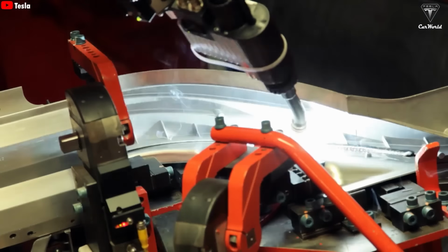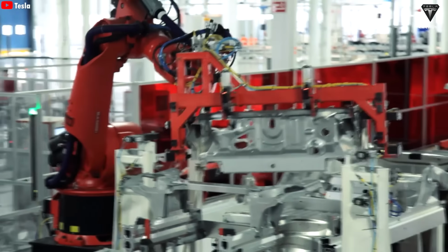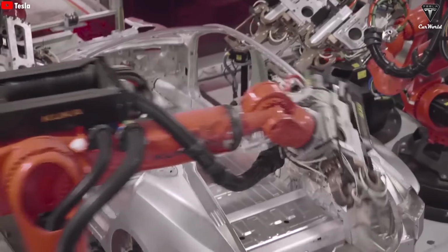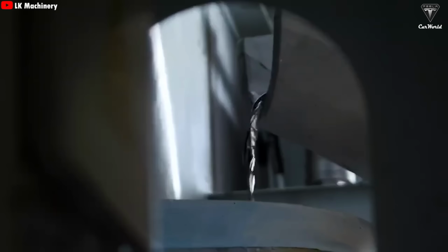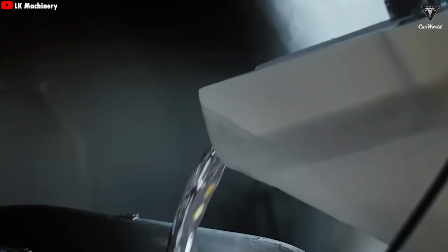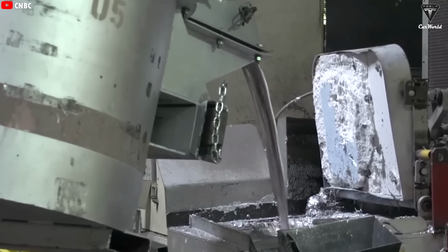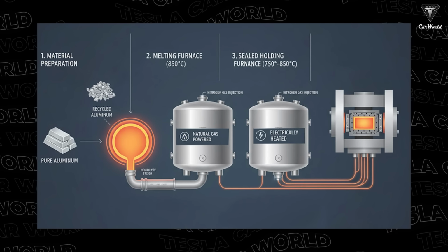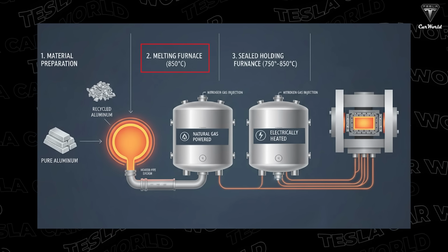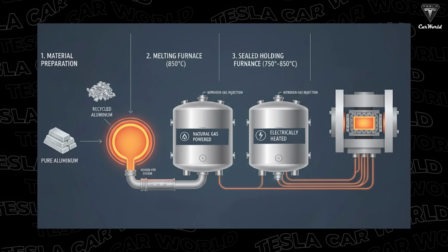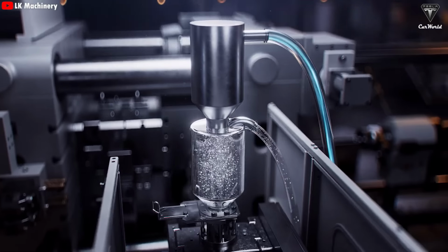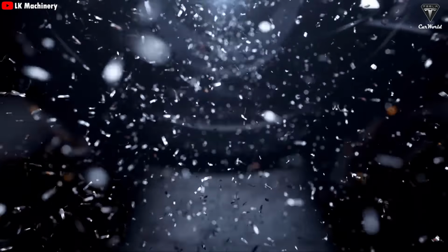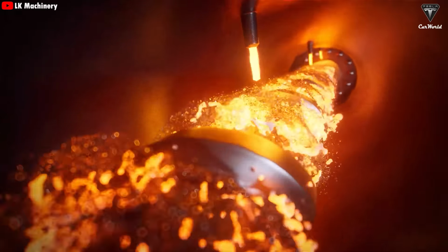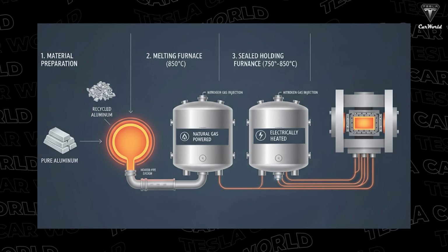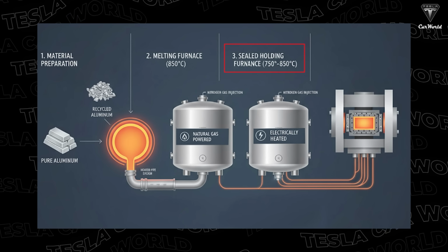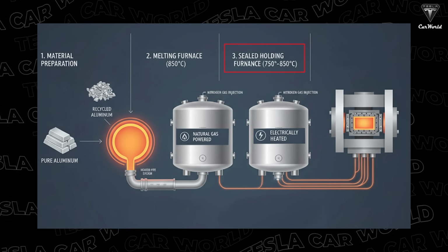As we know, most Tesla vehicles use aluminum chassis or body frames, and the Cybercab is no exception. With the new Gigapress, the process begins by melting new aluminum ingots together with leftover aluminum from previous castings in a furnace heated to about 850 degrees Celsius. After that, any surface impurities are removed before the molten metal is transferred through heated pipes into another sealed furnace, where the temperature is maintained between 750 degrees Celsius and 850 degrees Celsius.